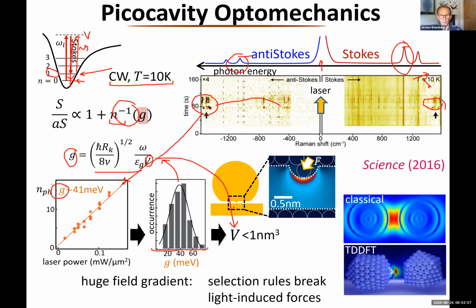So if you look in the very center of this nanocavity gap now, so this is the field of the gap, this is already the extremely enhanced optical field here, we get an extra enhancement. Whenever I get a gold atom pulled out of the facet, it actually has a concentration of optical field exactly like a lightning rod. So this is a lightning rod on the scale of a single atom, which you really have no right to expect. And this is a classical calculation, but if you actually do a time-dependent DFT, which is very difficult, you actually see the same thing, and it matches the classical calculation very well. So enormously surprisingly, you can actually account for this gold atom here using entirely classical theory.